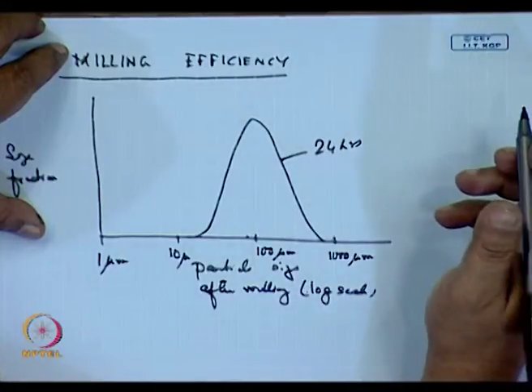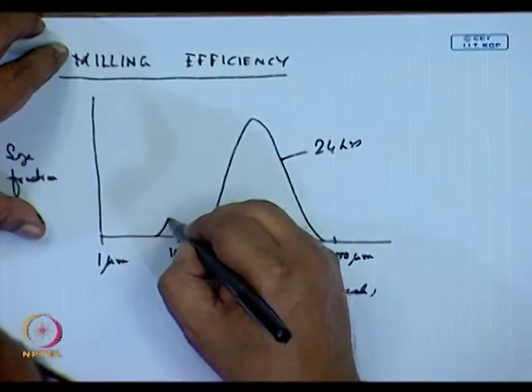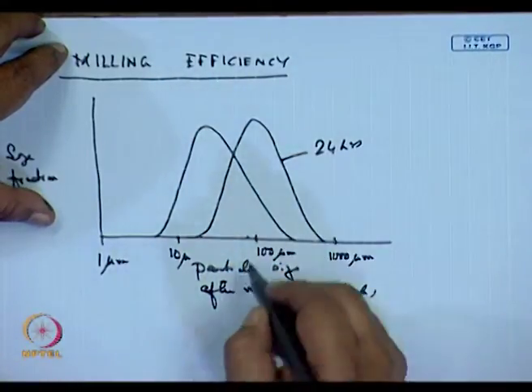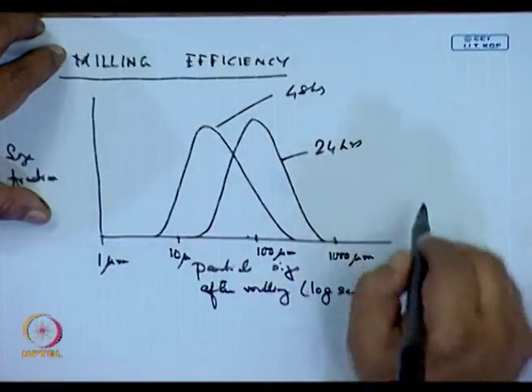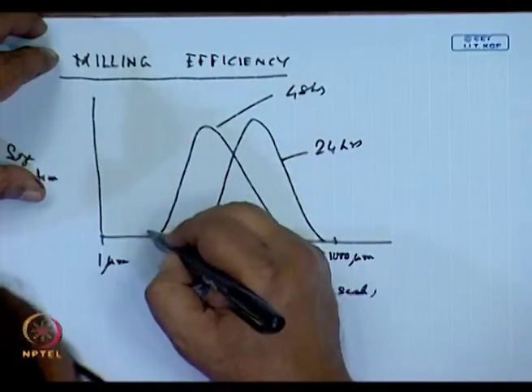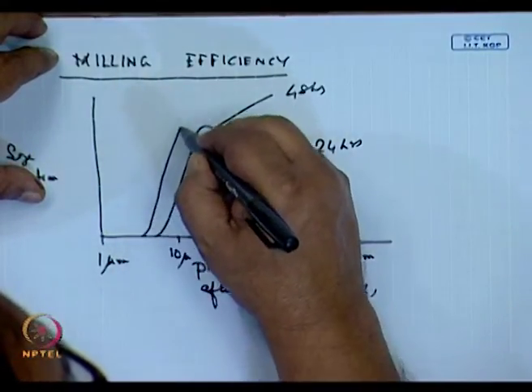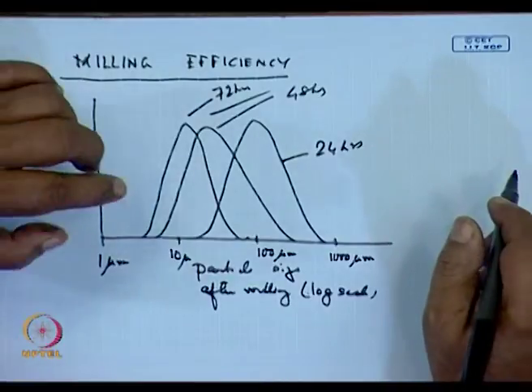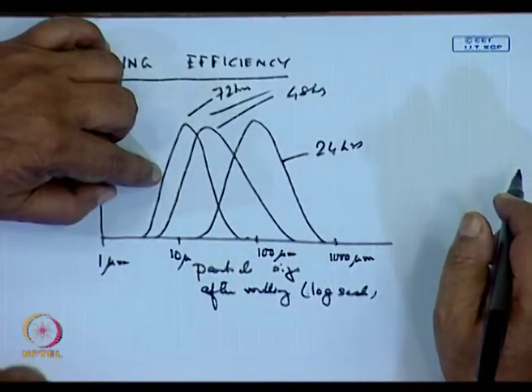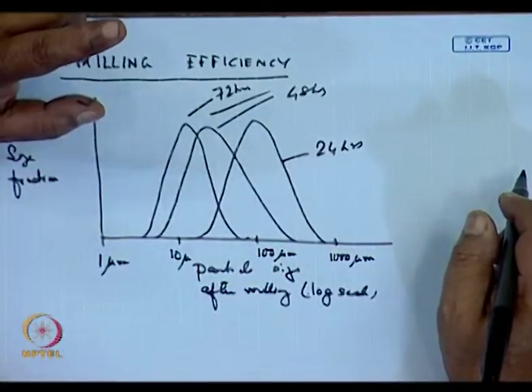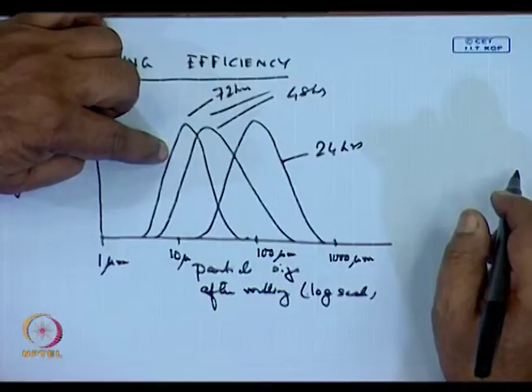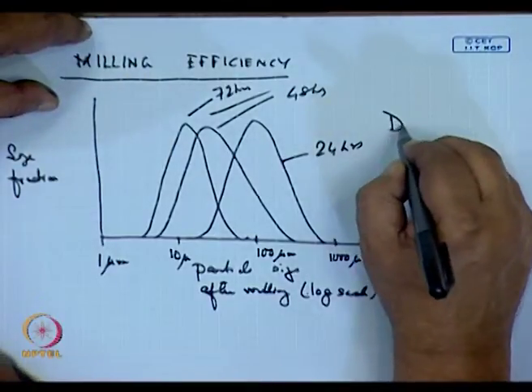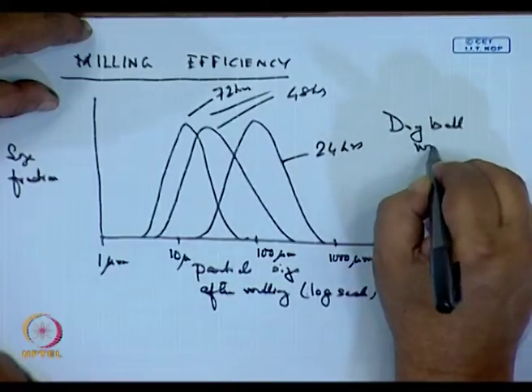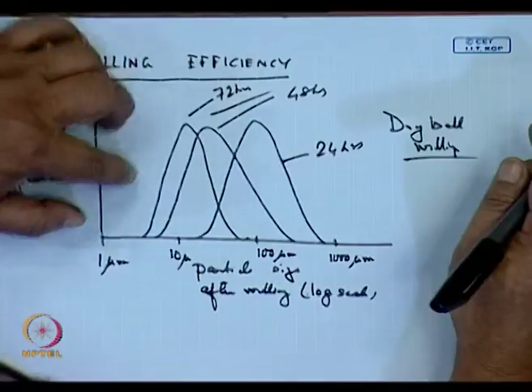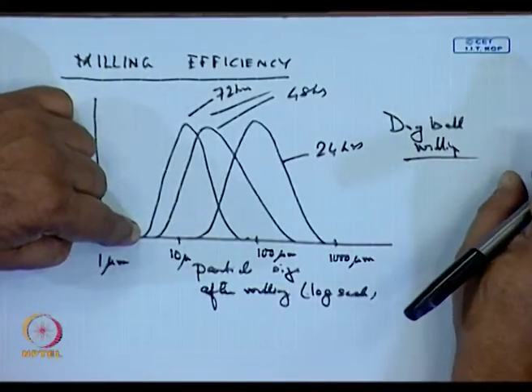Now, what would happen if I grind it for 48 hours? Maybe I would get something like this for 48 hours. What would happen if I keep on grinding it for 72 hours? This is where further grinding efficiency is not obtained. You can see the size reduction is not much. The amount of energy spent far outweighs the benefit of size reduction. So, in dry ball milling, due to various factors, we have a limit below which we cannot reduce the particle size.